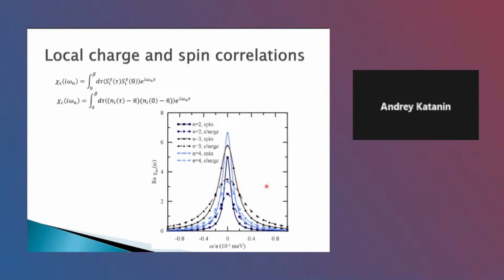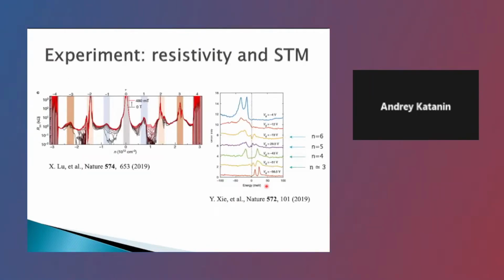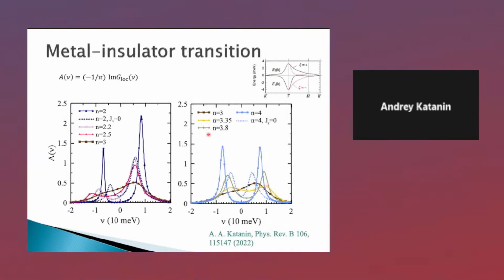The interesting point of these spectral functions is that these peaks are often associated with a Van Hove singularity. This is absolutely not the case, because if you look at the distance between these peaks, this is 20 meV, while the dispersion, the bandwidth, was several meV. And therefore, these peaks are just broadened atomic levels and have, in fact, nothing to do with Van Hove singularities.